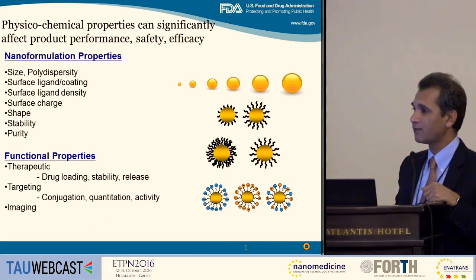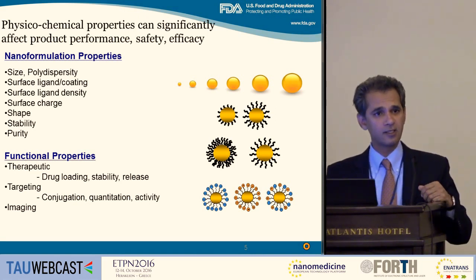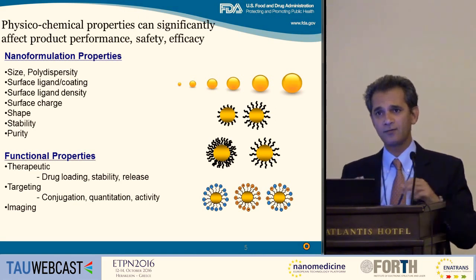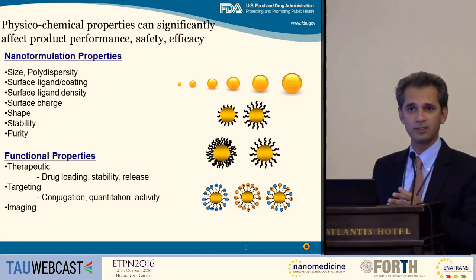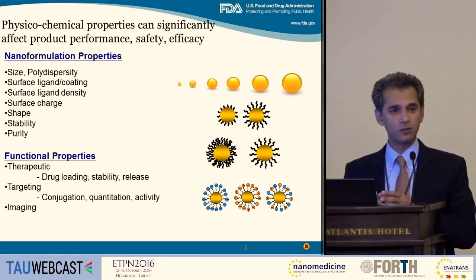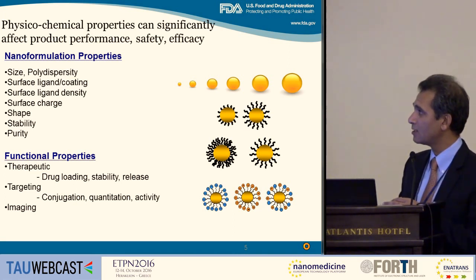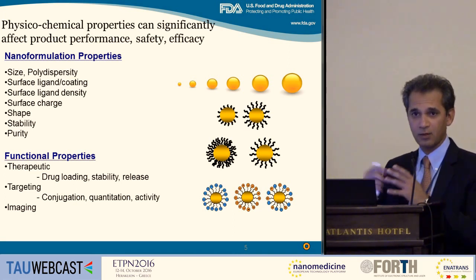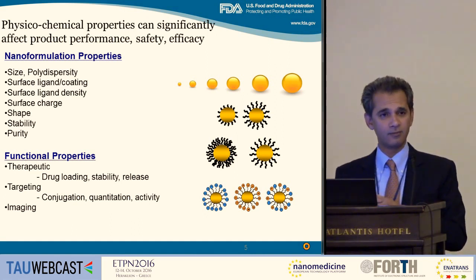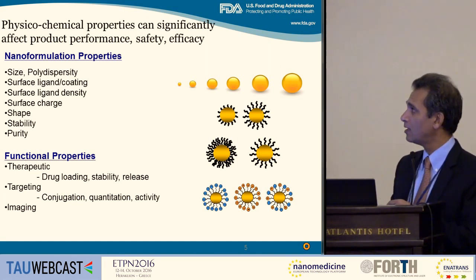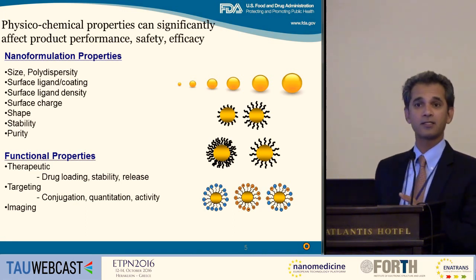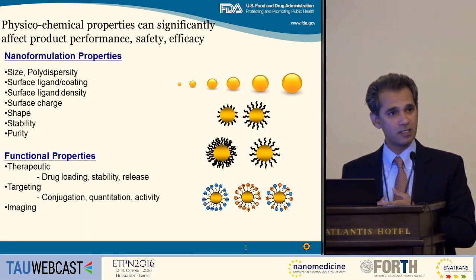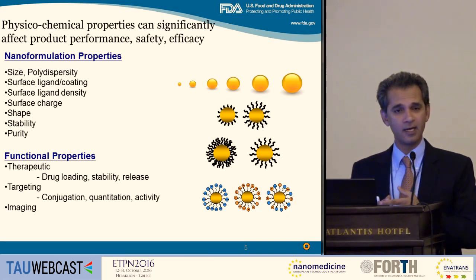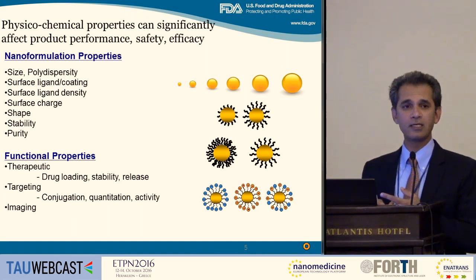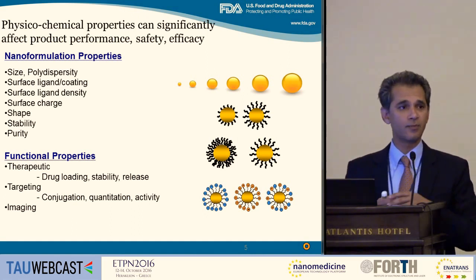Beyond size, you have many attributes. Most of the products contain some kind of coating, some kind of surface moiety. You have to see if it is covalently bound or if it is free in solution. In other words, a lot of publications in the literature, they take a nanoparticle, throw in some coating material. And what you have is a cartoon depiction of what you think it is, but that is not sufficient. You have to measure how much of the coating material is there and whether it is free in solution or it is bound to the nanoparticle. The reason that becomes important is the surface characteristics influence biological behavior.